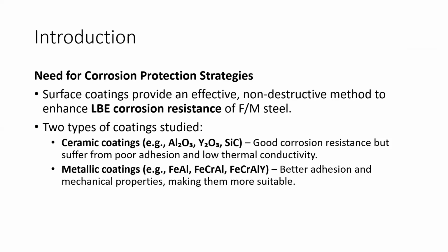Surface coating provides an effective non-destructive method to enhance LBE corrosion resistance of FM steel. Two types of coating are studied. One is ceramic coatings, like aluminum oxide, yttrium oxide, and silicon carbide. These have good corrosion resistance but suffer from poor adhesion and low thermal conductivity. Two is metallic coatings like FeAl, FeCrAl, and FeCrAlY. They have better adhesion and mechanical properties, making them more suitable.